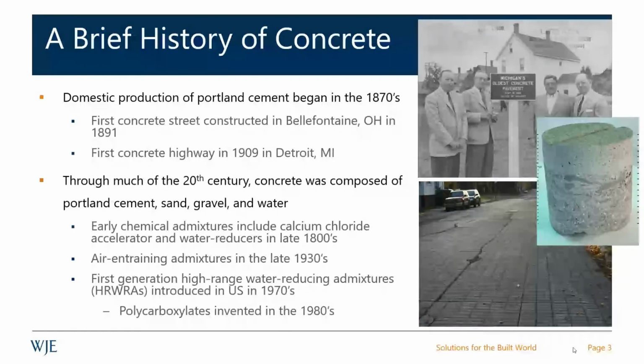And that picture, the lower picture, shows it more or less as it is today, and you'll see it's two-lift construction, which is pretty fascinating. Throughout much of the 20th century, we simply would take Portland cement and water, make a paste, and use that paste to bind sand and gravel together, sand and aggregates. We did start introducing early chemical admixtures, accelerators, and calcium chloride, some type A low range water reducers, really around 1900. Air entraining admixtures were discovered by accident in the 1930s, and are used to protect against frost damage.